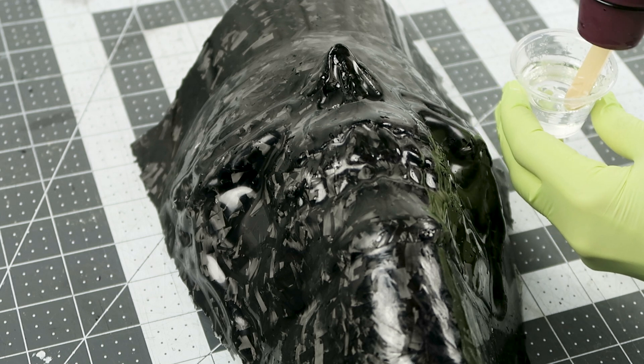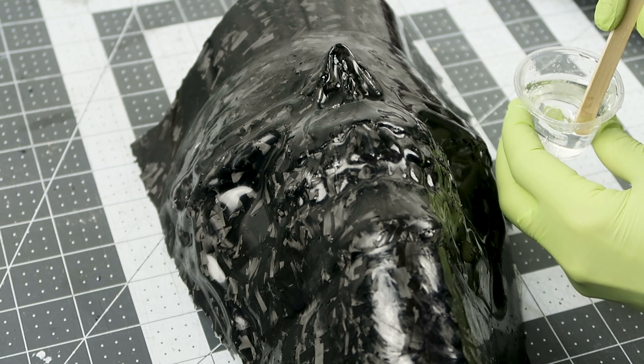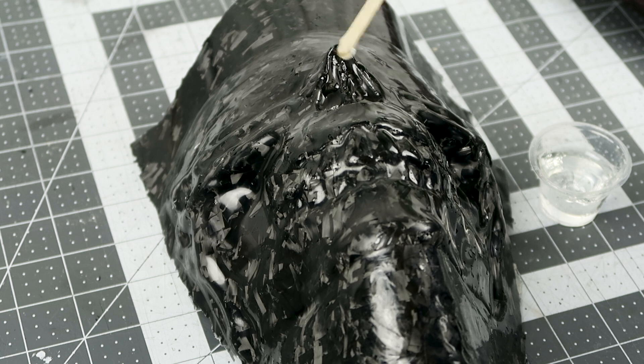This mask came out of the mold with a poor cosmetic finish and also some areas that are very sharp due to splinters from the forged carbon fiber not being pressed adequately against the sides of the mold.